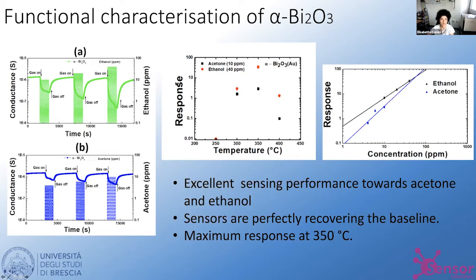So here we can see the functional characterization of bismuth oxide. And we have tested acetone and ethanol. And we can see that as the gas is introduced, we have a decrease in conductance and then back again to the previous value when the airflow is restored. We can see that we have a very high response, measured as the relative variation of the conductance over the baseline conductance, as 10 ppm or 40 ppm of acetone and ethanol are introduced in the test chamber. And this response changes as a function of the operating temperature. We can see that we have a maximum around 350.